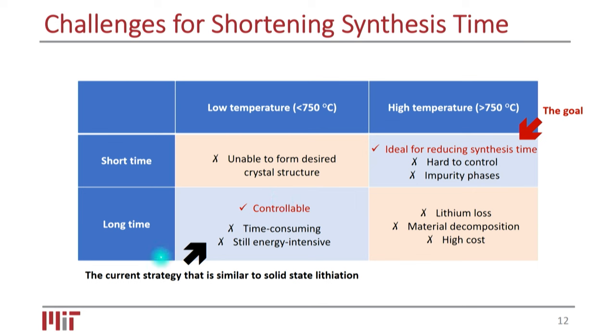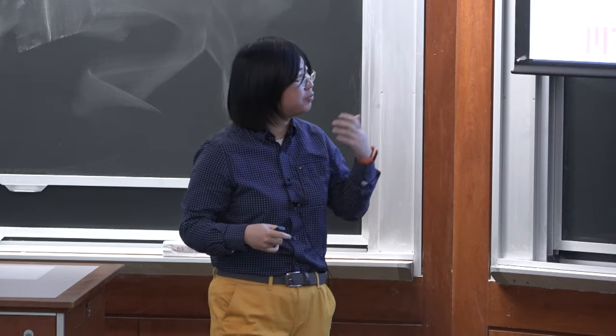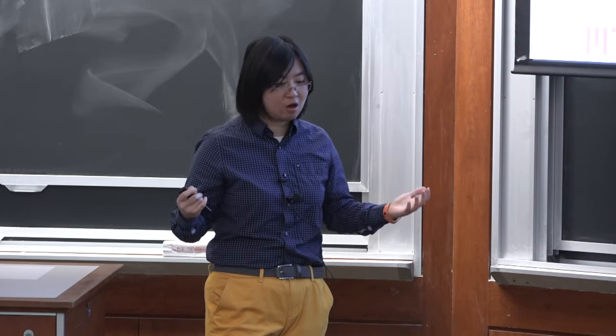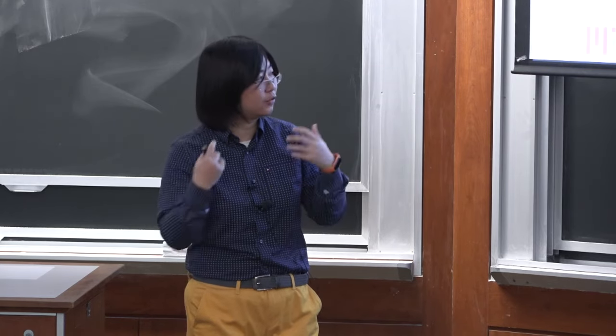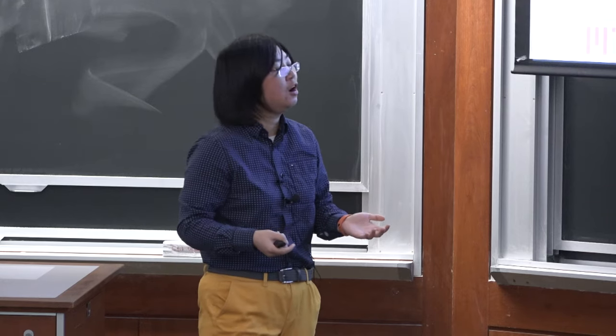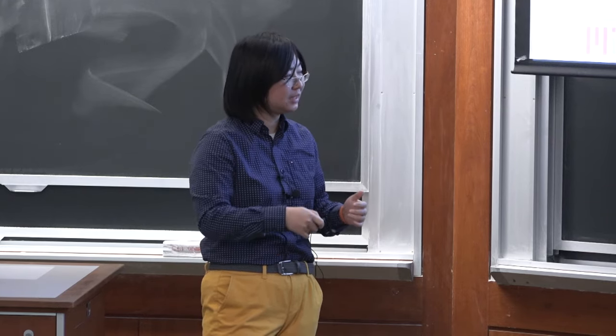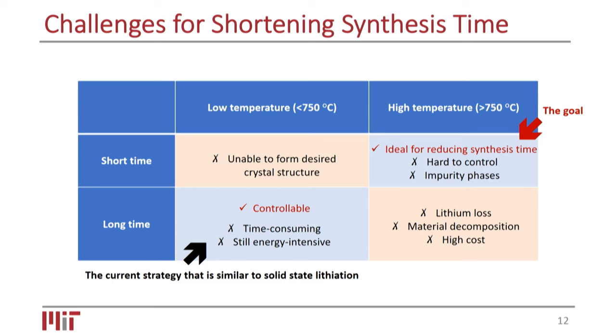The current step is this. We try to have a relatively lower temperature and relatively longer time for the calcination because we need to allow the diffusion to happen. We need to supply enough high temperature for this process to happen and a long time to have a controllable process for the diffusion and a uniform distribution of the multi-component inside the particle. Whereas what we really want to do is to go to this corner. We want to do things really, really fast so that we can significantly shrink the calcination time to save energy and time in the production.